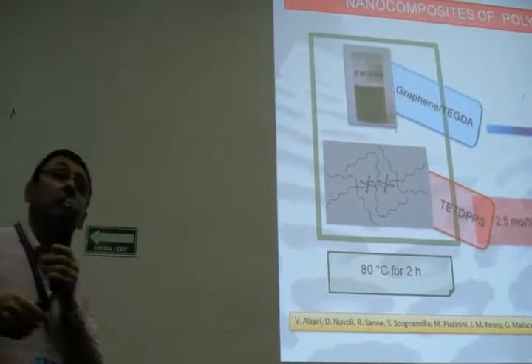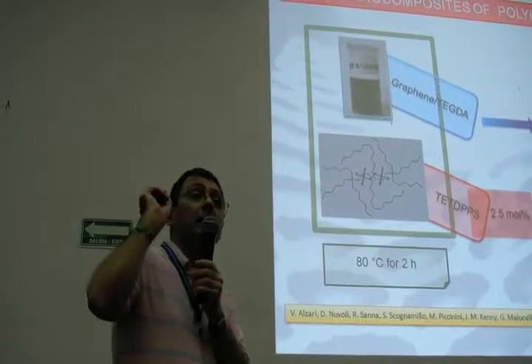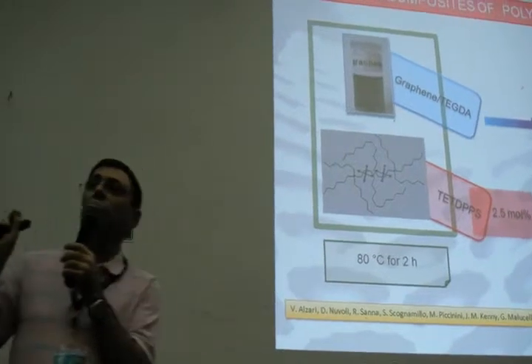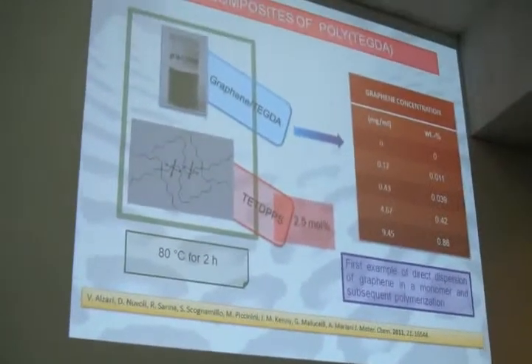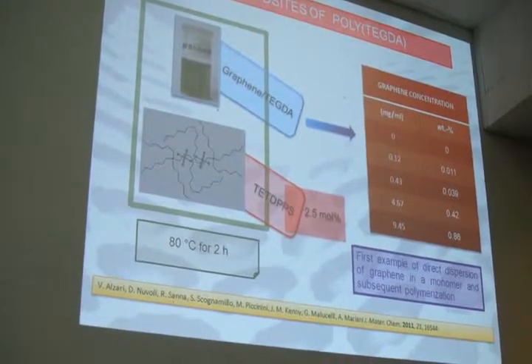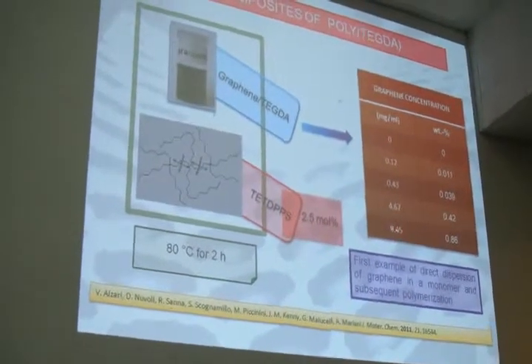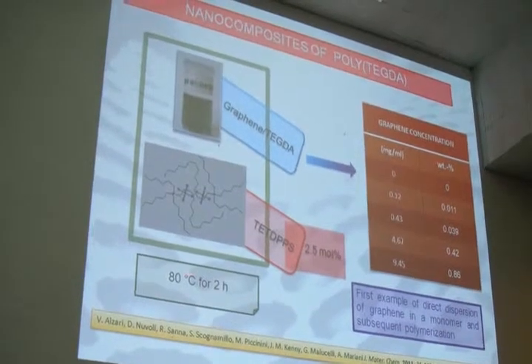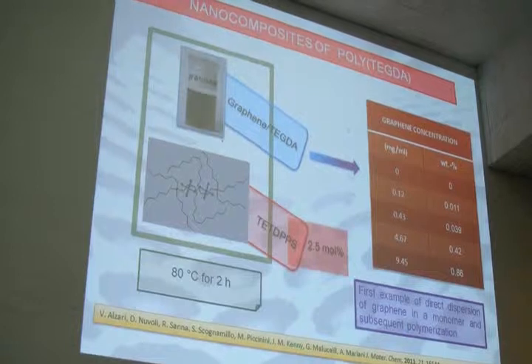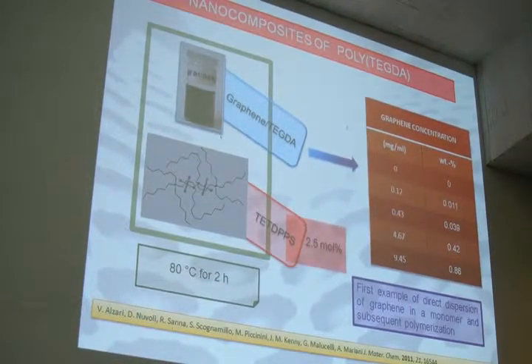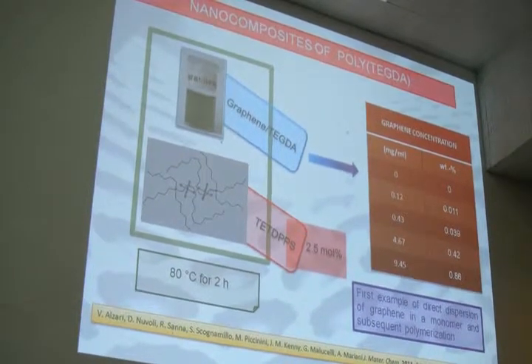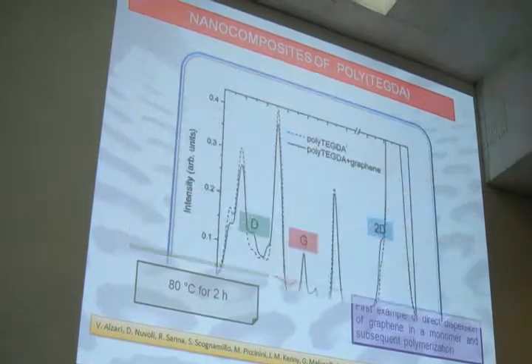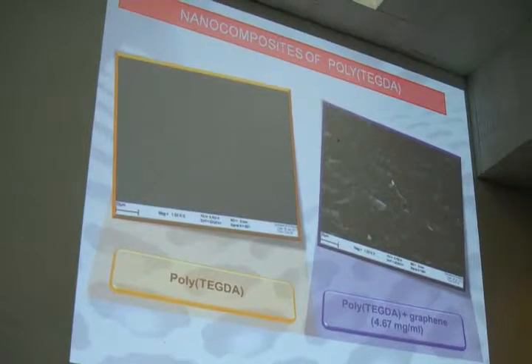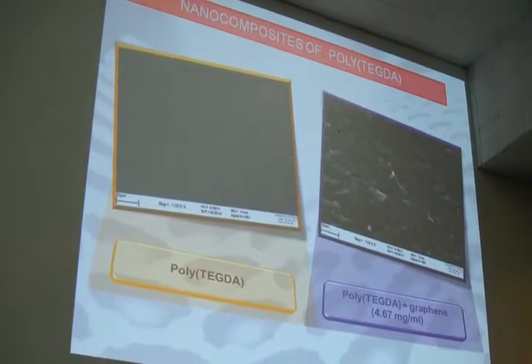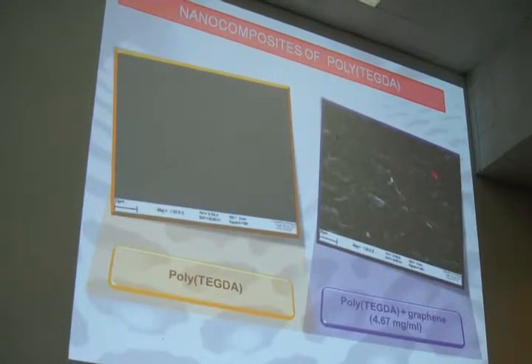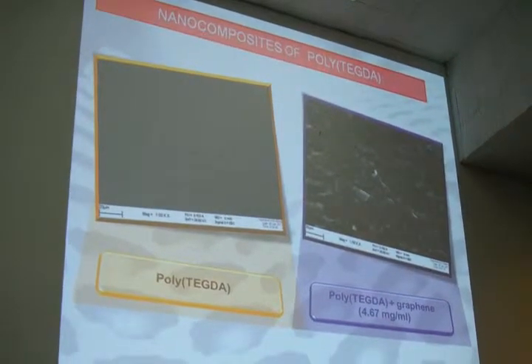The second system, just a couple of words about the second system. The second system is tetraethylene glycol diacrylate, a monomer, in which we directly dispersed graphene and then we polymerized it directly. The highest concentration is reported here. In this case, it was necessary to use frontal polymerization because graphene didn't reaggregate during the polymerization process. Scanning electron microscopy, I hope it's visible. This is the neat polymer, and this is the nanocomposite. You can see the big difference between the two images.